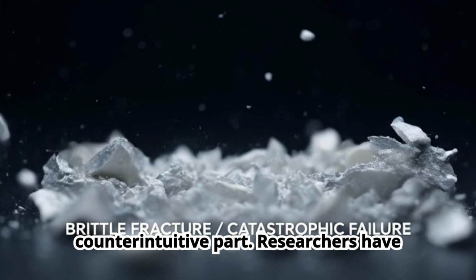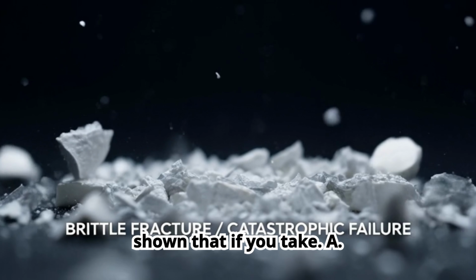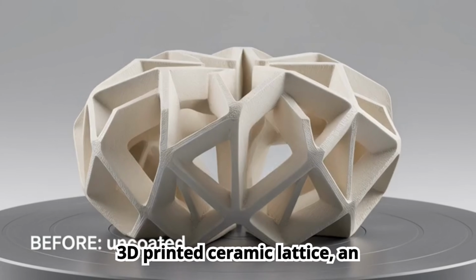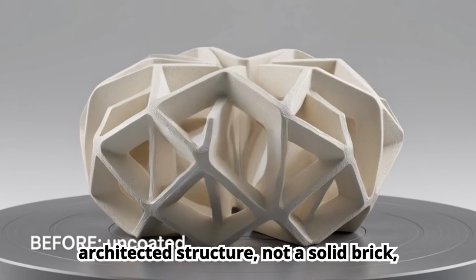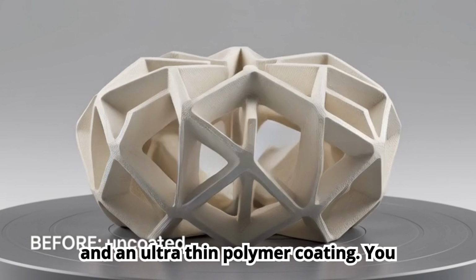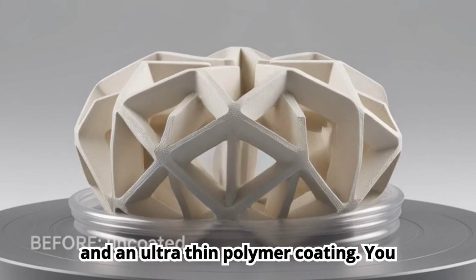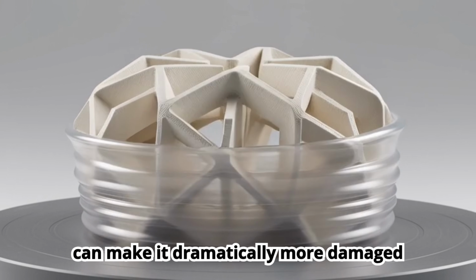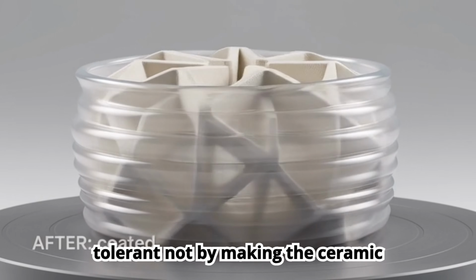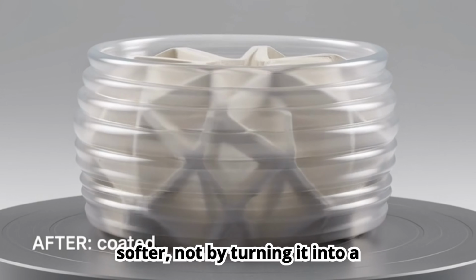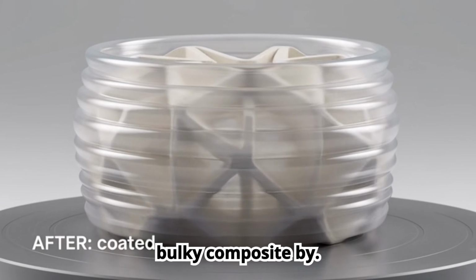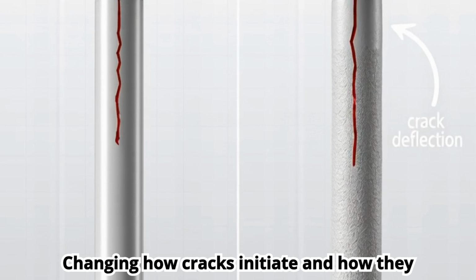Now here's the counterintuitive part. Researchers have shown that if you take a 3D printed ceramic lattice, an architected structure, not a solid brick, and add an ultra-thin polymer coating, you can make it dramatically more damage tolerant. Not by making the ceramics softer, not by turning it into a bulky composite, but by changing how cracks initiate and